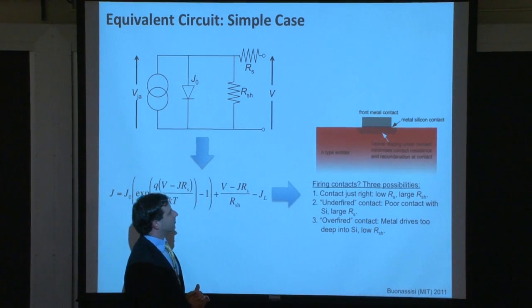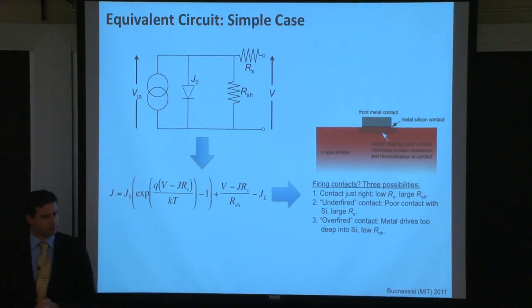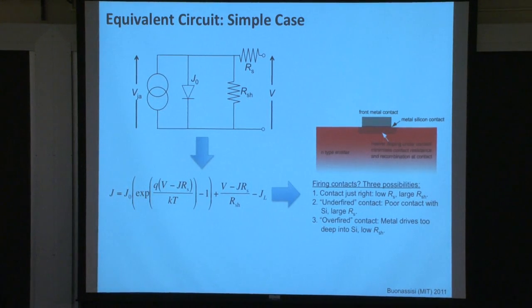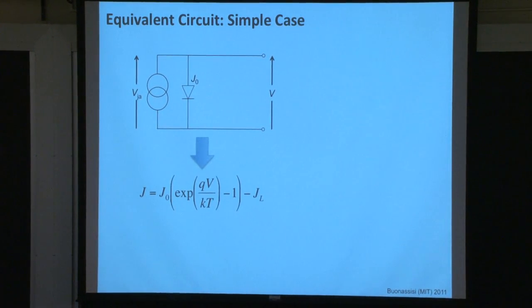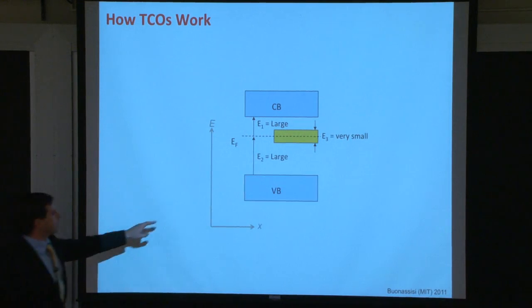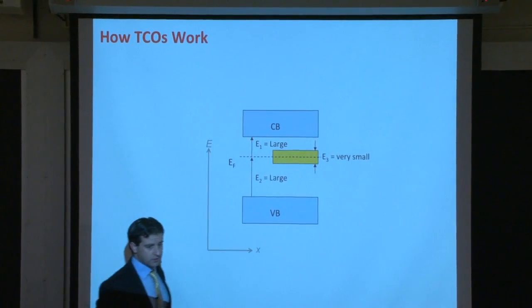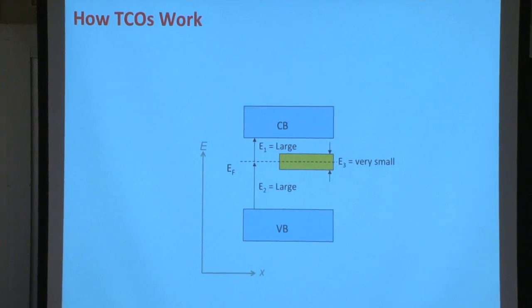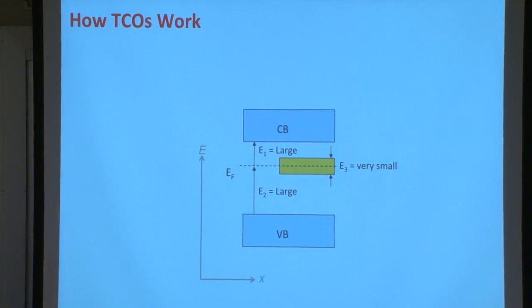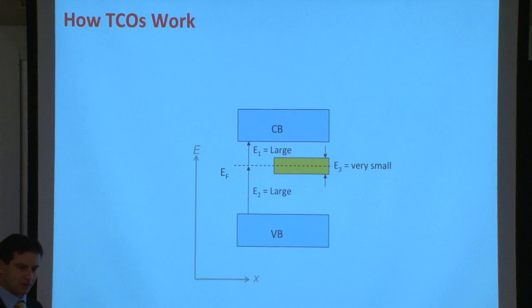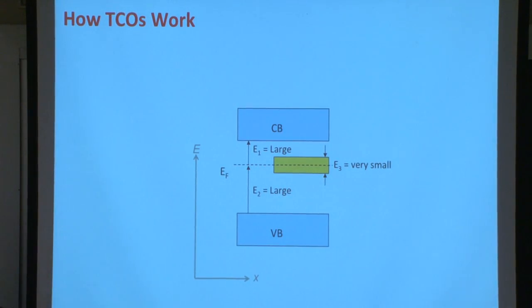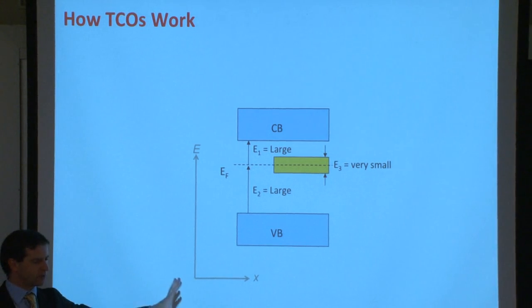For a TCO, it's a little less straightforward because you typically have a multinary compound, meaning several elements comprising your TCO. The formation of this intermediate band right here that forms really the conductivity of the TCO is predicated upon the principle that you have these dopant atoms homogeneously spaced throughout your material. If you heat it up too high and they begin to cluster, in other words, precipitate out of phase, you can wind up destroying your TCO or increasing the resistivity, maybe even decreasing the optical transparency. And so it really is material specific when we start talking about TCOs.